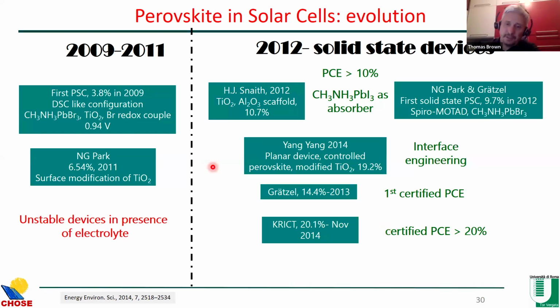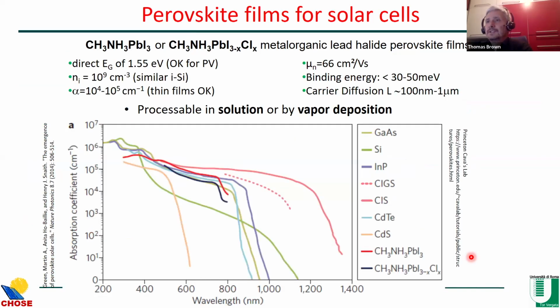Between 2009 and 2011, they were being used for replacing dyes or together with dyes in dye-sensitized solar cells, but the devices didn't really work so well because of the electrolyte. Then Snaith and Grätzel's group in 2012 used a solid state configuration and achieved over 10% efficiency. So that was a major breakthrough. And things have been improving over the years. And just in 2014, the first certified power conversion efficiency of over 20% was produced by KRICT in South Korea. Now the efficiency is over 26%.